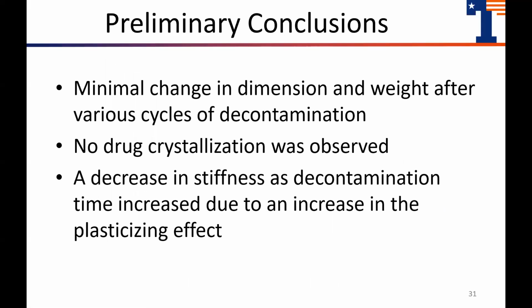So our preliminary conclusions for the initial research is that there's minimal changes in the dimension and weight after various cycles of decontamination. There was less than a 5% decrease in the weight, indicating that the PLA fibers were being slightly degraded, and there was also an increase of 3% in the dimensional change, but that wasn't very significant. And from the naked eye, there was no obvious signs of deformation or any degrading happening. From the fiber microstructure, we were able to see that there was no drug crystallization occurring as the decontamination time increased. And then lastly, there was a decrease in the stiffness as the decontamination time increased due to an increase in the plasticizing effect.